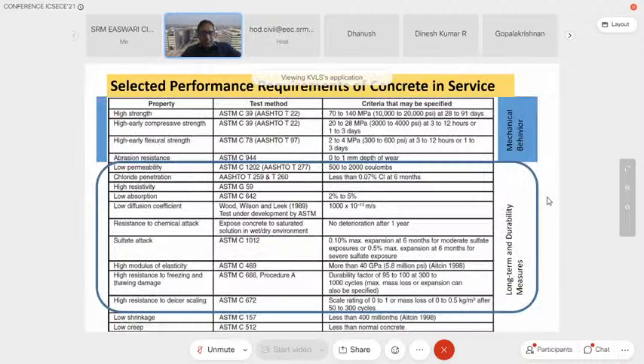So there are different test procedures, like I mentioned, that have been developed for measuring different things. If you look at this left-hand side column, that is the property being measured. We are all very familiar with the strength. That is the very first row. But if you come down here and you look at the blue box, these are the performance measures, the long-term durability measures. And now accelerated test procedures have been developed. And now we can specify performance of concrete in these tests and say concrete should be able to achieve this level of performance in a chloride penetration test, which would assure that if you put that concrete for use, let's say in a marine environment, it would be able to withstand 200 years of service life. These are the kind of requirements that are going to come in place, where now we will specify the performance requirement of concrete, which will ensure a long-term durability of the structure.